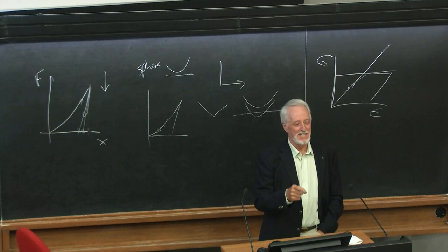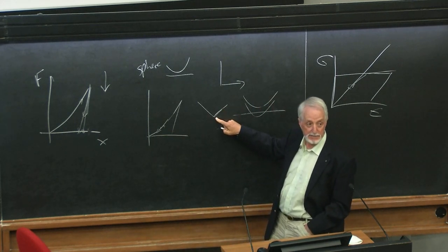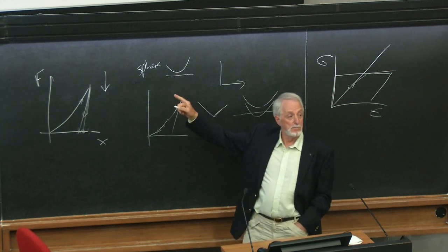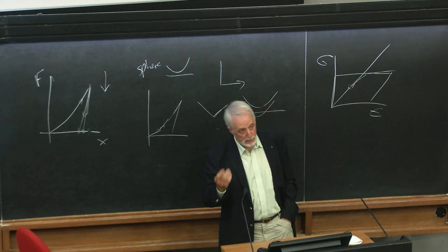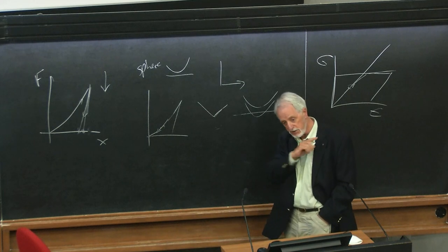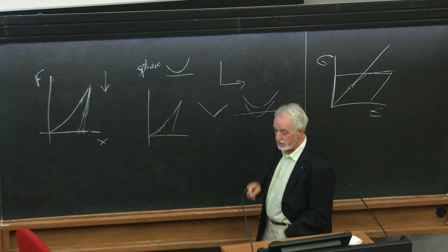But this works basically because in something like that, which is very sharp, you're always going to get some plastic behavior at the tip, okay? With something which is round, there's a risk you're going to move more towards this kind of thing we're familiar with, certainly weak plasticity and even elasticity. It approaches more towards, as we'll see at the end of the talk, what's familiar in this community. Here, you definitely get plasticity.